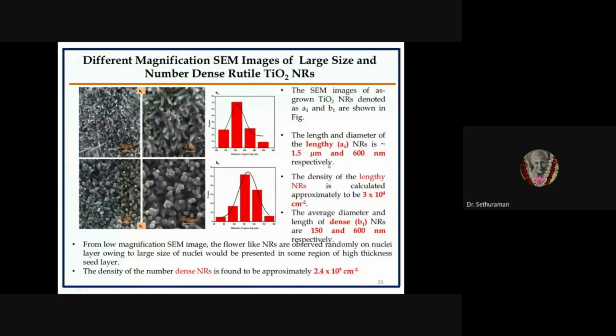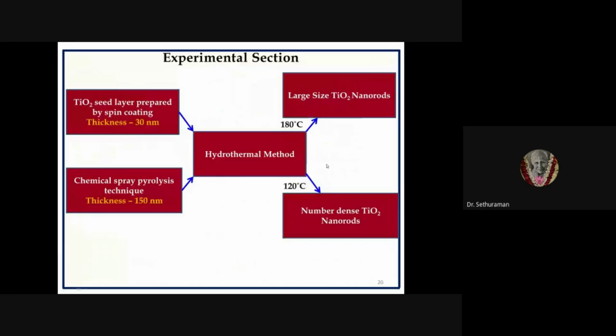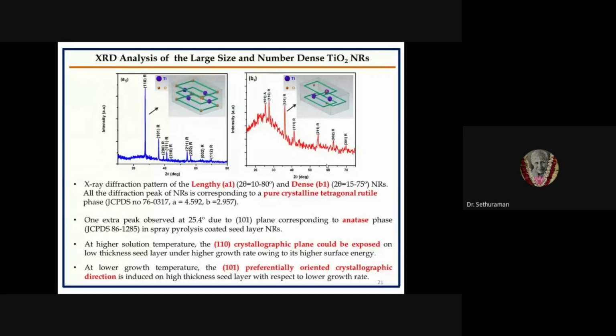So in the first case, at 180 degrees Celsius, we prepared large size TiO2 nanorods, almost 1.5 micrometers in size, on the surface of the seed layer. In the second case, at 120 degrees Celsius growth temperature, we obtained a high number density of TiO2 nanorods.